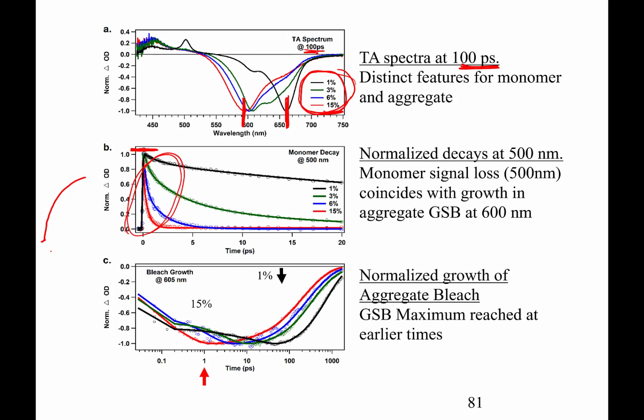So here's the normalized growth of the aggregate bleach, and it is hard to see in here, but the peak here for the 15% sample, which is red in here, we hit that maximum amount of aggregate at about 1 picosecond. So it doesn't take much time to reach that, whereas with lower concentrations, at 1%, it takes about 100 picoseconds to start to see some of that ground state bleach for the aggregate state.